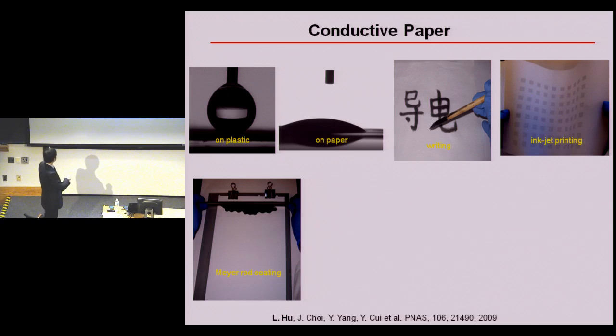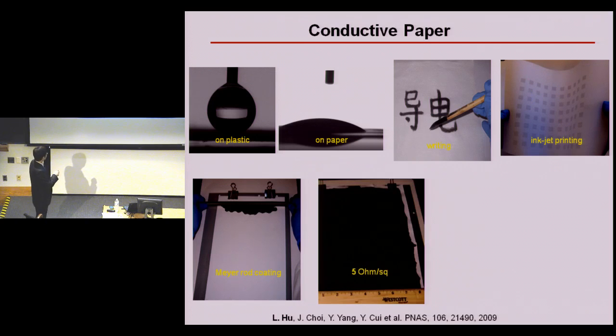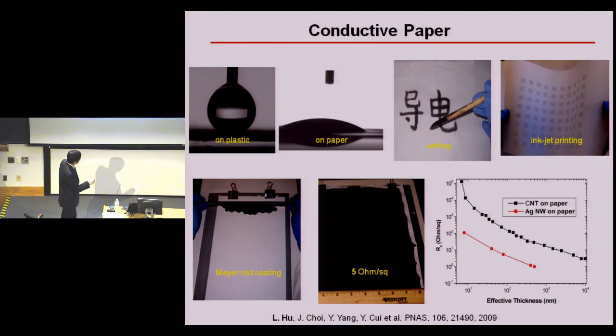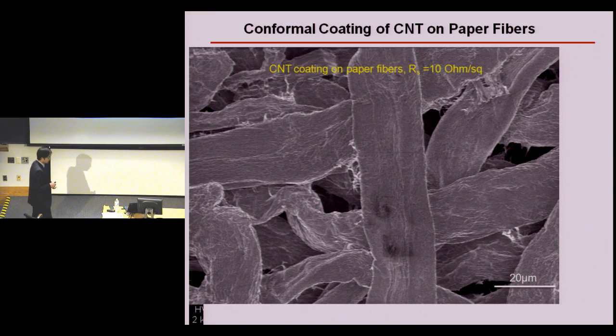So we can also do this kind of Meyer rod coating. Very quickly after this coating process, we can turn the insulating paper into a highly conductive porous medium with the sheet resistance in a range of a few ohms per square. So this highly conductive paper is actually very promising for energy device applications.